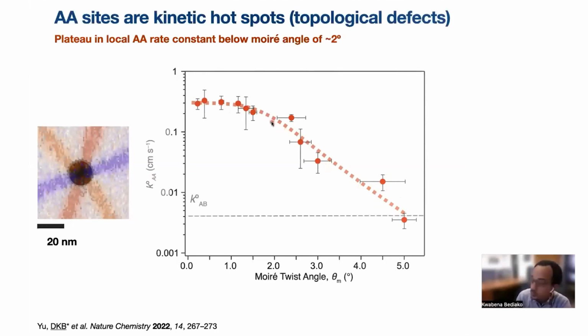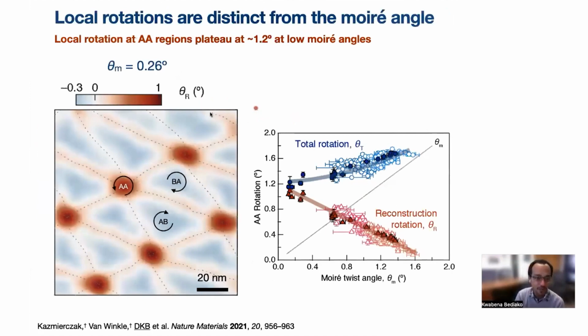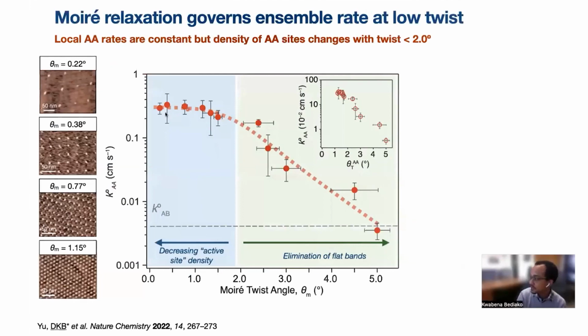And so already you might be seeing how these two things are related, because knowing that the AA sites plateau in their activity, you can understand this from the perspective of the local rotations that we've measured. We know that the local rotations are distinct from the initially imposed Moiré angle, and that the AA regions locally plateau at about 1.2 degrees. We measured that. And so the reason that the AA sites also attain a plateau in their local electrochemical activity is because their local rotations are all constant. In other words, their local electronic structure is, for all intents and purposes, at room temperature, the same, irrespective of the Moiré angle.